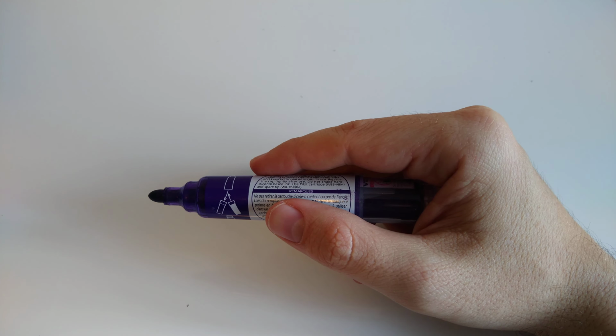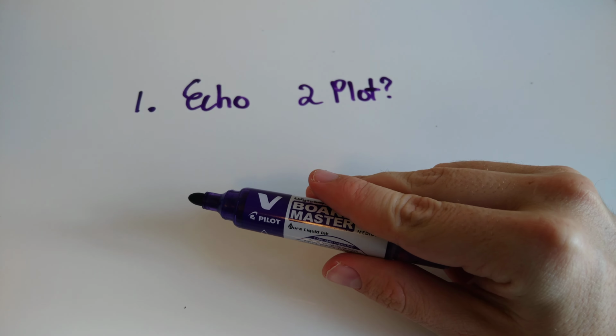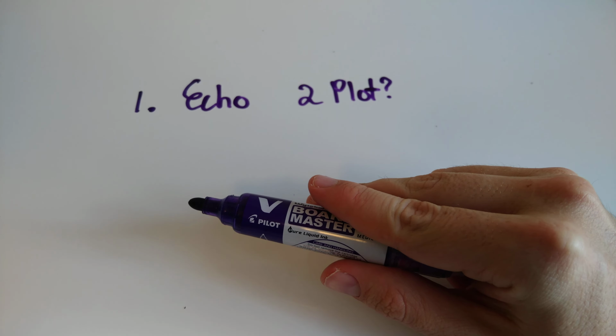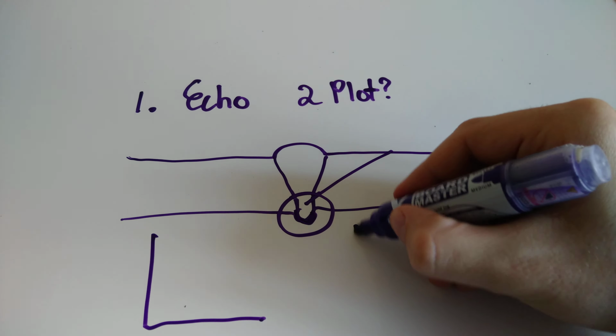I always check for two things, which is the echo pattern and where does my defect plot out. Those are the two things that I always check when I do conventional UT with an A-scan representation. So, for example, if I have a weld here like that, and I'm getting echoes that plot out in this area. Now I'm talking about defect echoes, not your general geometric root echo, but something that should not be there. It's going to be one of two patterns typically.